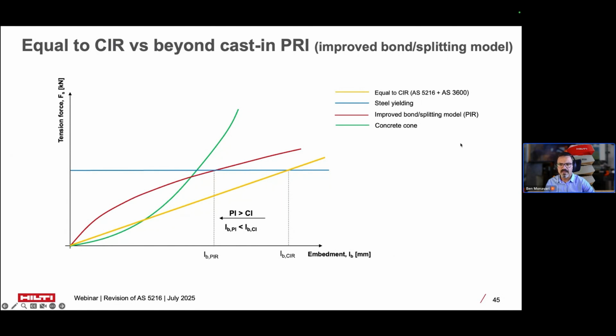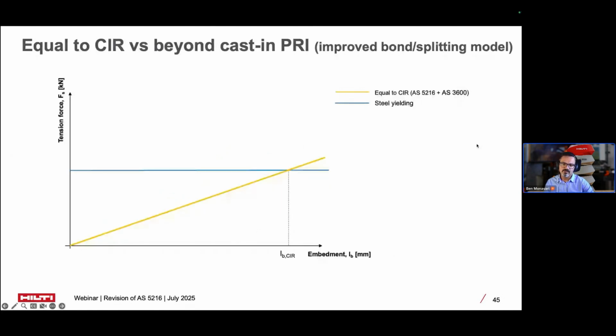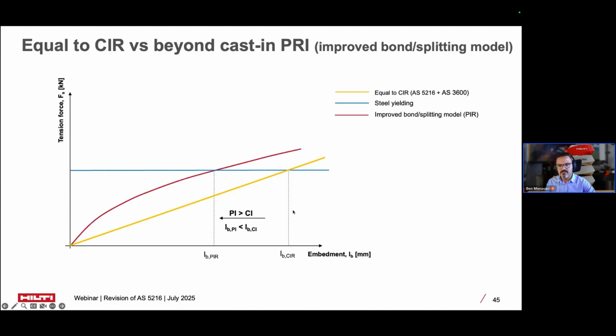So if I go back to the first slide, in equal to cast-in, we assume we have a linear relationship between the embeddment depth and the capacity of the post-install rebar or cast-in rebar. So this is the equal to cast-in method. As you can see here, this is a linear relationship. And if you want to design for yield, which is the blue line, we need to drill to this depth. But within the new design method, because we are utilizing the higher bond capacity of the chemical, we are having higher capacity, but as you can see here, it is not a linear relationship anymore.